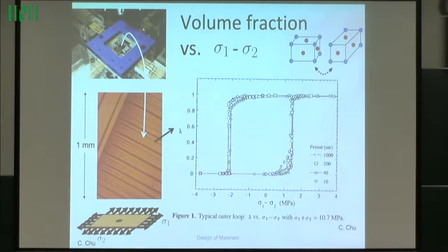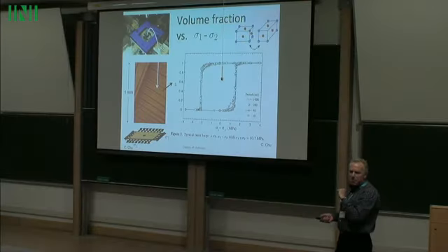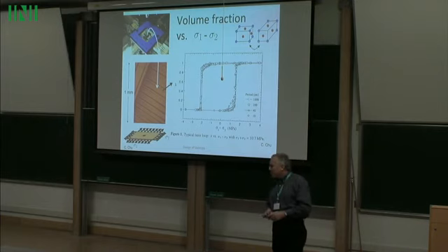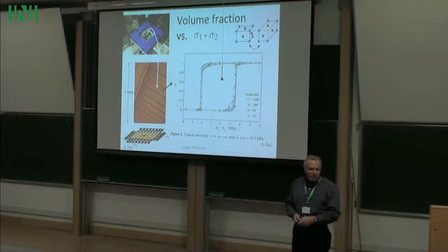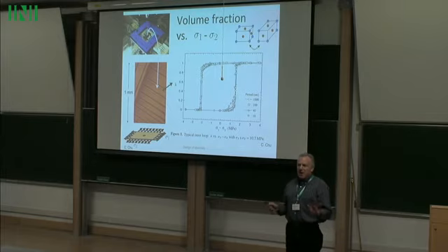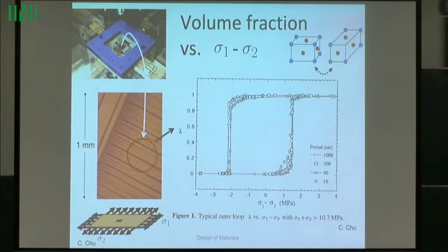But the main point is that there's a part of the hysteresis, the main part, in which if you go around the hysteresis loop slower and slower and slower, it does not collapse to zero. So if you're a mathematician and you're used to modeling dissipation with some rate laws or some viscosity or some viscoelasticity, that's wrong. That would be the wrong model because it would not have this property of rate-independent hysteresis. The hysteresis loop would collapse to zero if you went slower and slower around the loop.